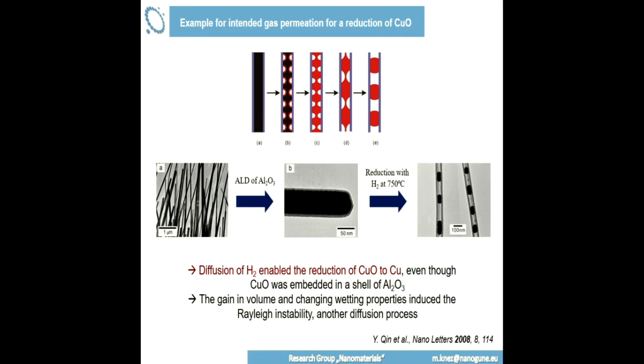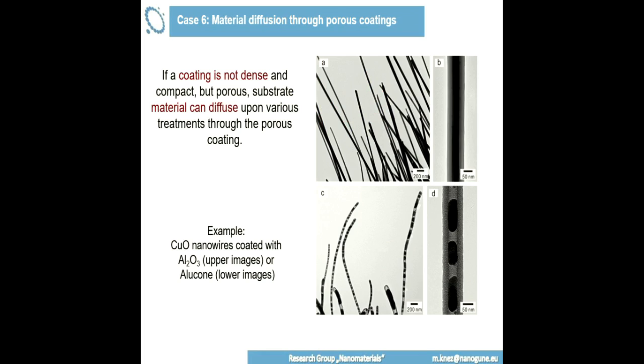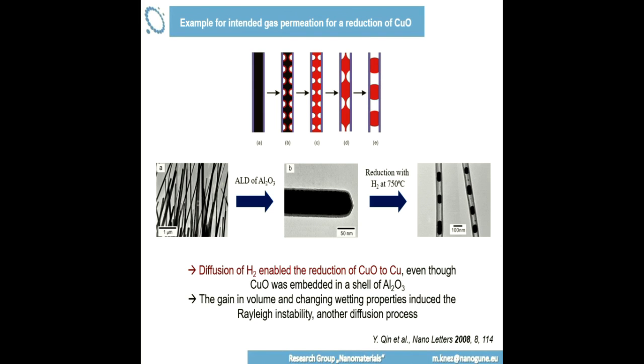And of course, copper oxide has a larger volume than copper. That means you have a shrinkage of the material inside here. So this coating, even without being cracked or defective, will allow gases to pass through. Of course, it depends on the type of gas. A small molecule like hydrogen will go through more easily than water or whatever. But still, you have the permeation possibility. That means here you reduce the volume, which is an indication that you really reduce the copper oxide to copper. That means this really works without even cracking the film. The film itself is permeable for many of the gases.